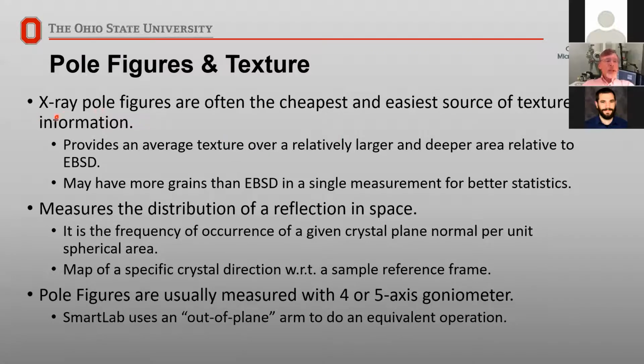So we can actually measure the amount of this texturing, as we call it, by doing X-ray pole figure analysis. You can do the same thing in an SEM with EBSD analysis, but the X-ray pole figures will give you an average texture over a larger area and also deeper relative to the EBSD. EBSD is very sensitive to surface damage in your material, so you're only analyzing tens of nanometers deep, whereas this can go microns to tens of microns deep. And depending on your grain size, you may actually wind up with more grains in a single measurement using the X-ray than you do in EBSD. So you may be able to get better statistics. EBSD, however, will show you the relationship between the adjacent grains, which is something that X-ray can't do.